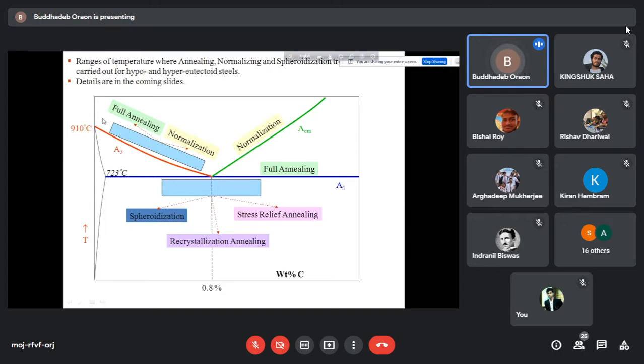So this whole region, starting from this point on the left-hand side and going above the upper critical temperature, is called the normalizing region. And when you are talking about full annealing, it starts from this side, and when the percentage of carbon is more, that means beyond this eutectoid point, the full annealing is just above the lower critical temperature. So identifying these different zones is very important, so that given a particular specimen, you know what temperature zone you'll have to heat the material in, and keep that material for some time at that temperature. So that is very important. These are the two important heat treatment processes: full annealing and normalizing.